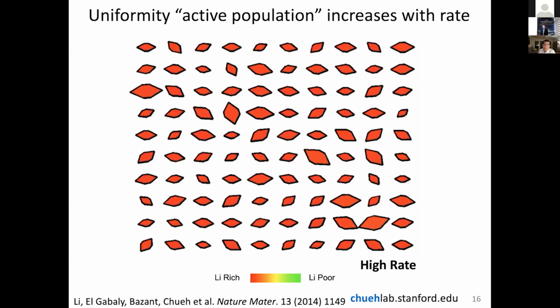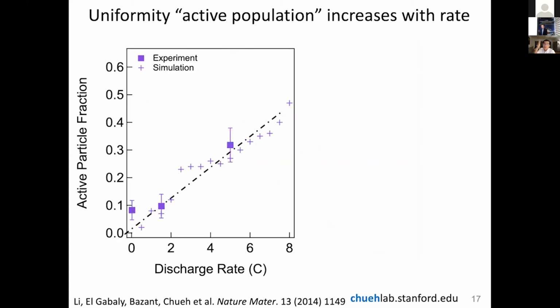So here we have a very uncomfortable observation where the system is extremely heterogeneous when it's close to equilibrium, and the system is very homogeneous when it's far from equilibrium. So let me plot this for you. This is the active particle fraction. So this is the percentage of the battery electrode that is participating in intercalation. And then the bottom is C rate. So higher the C rate, the faster the reaction is. So you can see here at very low C rate, almost none of the battery electrode is active, as I showed in the movie before. But as you increase C rate, more and more of the electrode becomes active.